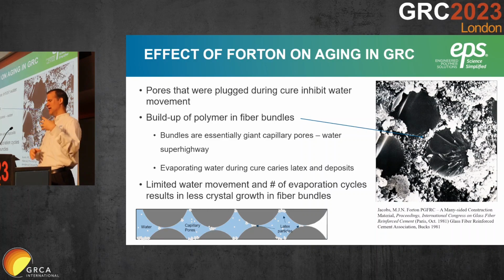How do polymers work in there? Just like when the cement is curing, you've got water that's evaporating. There's a lot of space that those small latex particles can get into. When the water evaporates, the polymer particles can't, and they will build up in these fiber bundles. The bundles are essentially giant superhighways for water, and anything smaller can travel through there very quickly, but the polymer will get in there and bind. What that does is control the movement of water. The slower the water goes in and out of the system, the less the calcium hydroxide is going to dissolve and build up in other spaces.